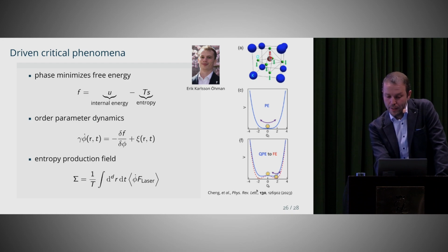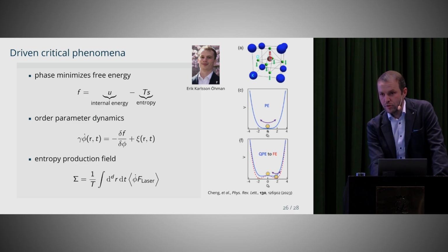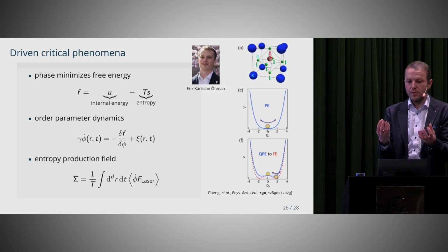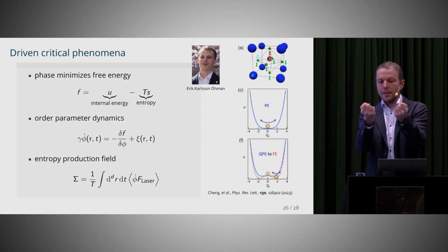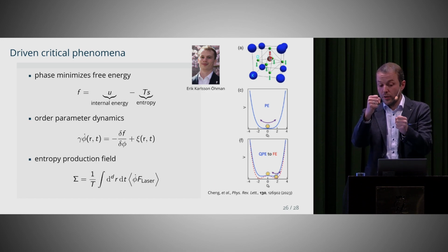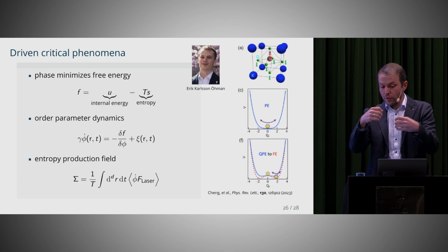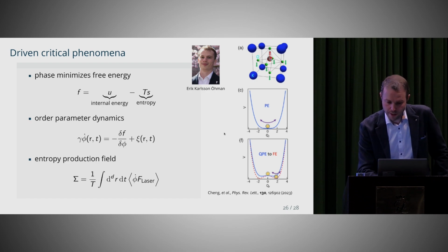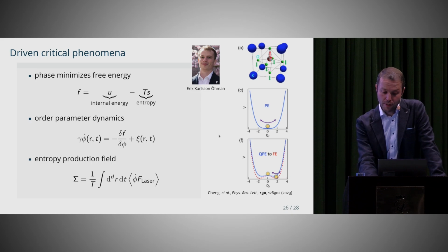And again, to the right, I want to show a picture of an experiment which we have in mind. There is a group also at Stanford, which shows that with a laser field, you can control the so-called energy landscape of a material. So they now talk about ferroelectricity. That is a situation where atoms spontaneously want to slightly displace and induce local dipole moments. And they show that if they come with a very short laser pulse, the atoms can be stuck in this configuration, so they don't want to go back. And we believe that entropy production is a key concept in this process to understand.